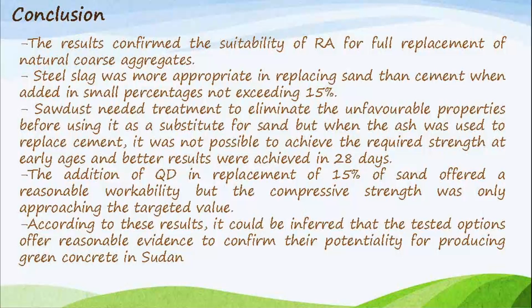So sawdust needs treatment to eliminate the unfavourable properties. The addition of QD replacement of 15% of sand offered reasonable workability, but the compressive strength was only approaching the target value. According to these results, it could be inferred that the test options offer reasonable evidence to confirm the potentiality for producing green concrete for Sudan.